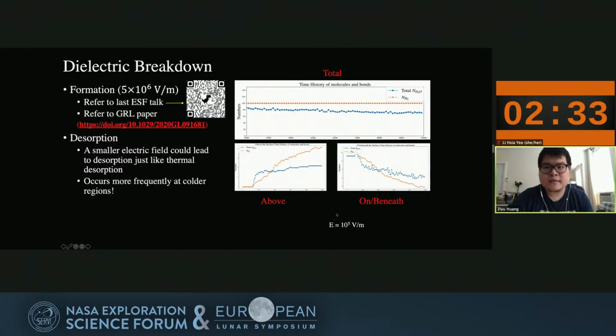When applied an electric field of about the order of 10^5 volts per meter, the total number of molecules stayed relatively stable, meaning that the electric field won't break H2 or H2O. But the hydrogen molecules and also water molecules are leaving the surface. That can be seen from the lower two figures. And in contrast to thermal desorption, this occurs more frequently in colder regions.